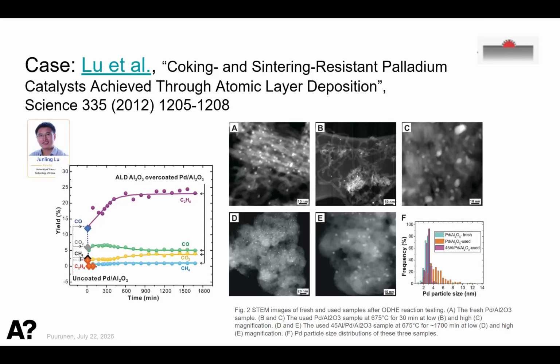This is from the Science journal, 2012, where exactly this overlayer has been grown on palladium on alumina, and the overlayer was also alumina. This overlayer has protected the catalysts from deactivation in two ways. The oxidative dehydrogenation reaction with overcoated catalysts worked, whereas it really didn't work with the non-overcoated normal ones. If you examine this further, in the normal catalyst there was a severe problem of coking and also of sintering, whereas in the ALD coated ones, both of those are absent. So the particle size has remained small, and you also cannot observe those whiskers.